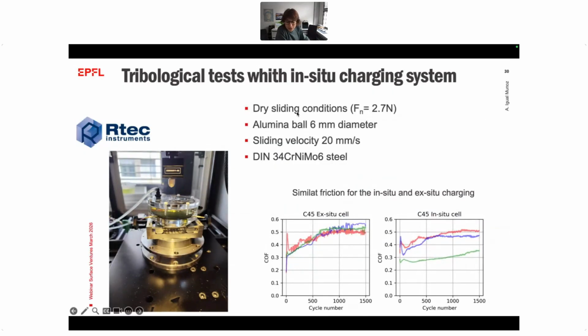We can wear against an alumina ball, the same conditions as we did with the ex situ experiments, the same sliding velocity, the same normal force. And what we see, if we compare the coefficient of friction, is that we start seeing some differences between the tribological response in the ex situ cell compared to the coefficient of friction in the in situ cell. This is under dry conditions.